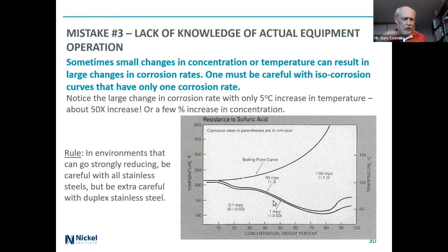And whenever I look at iso-corrosion curves, I want to see more than just the one line. Most iso-corrosion curves show maybe 0.1 millimeter a year or something in that area. I want to see more lines on that curve. With stainless steels, you need to be careful, but especially duplex stainless steels, they are more sensitive to going from the passive state to the active state, and with relatively high corrosion rates in the active state.